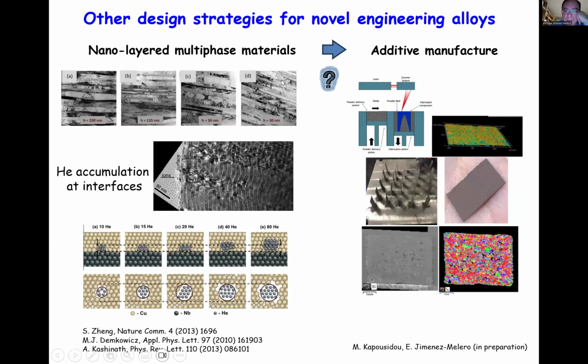Very quickly, there's quite some work being done at the moment to try to optimize the interfaces of the material, create multi-layer materials to actually reduce the damage or the helium formation, both with simulations and with experiments. And we are also exploring the idea of near net-shaped components by additive manufacture. So ideally, we will not need much more machining or shaping after that additive manufacture.